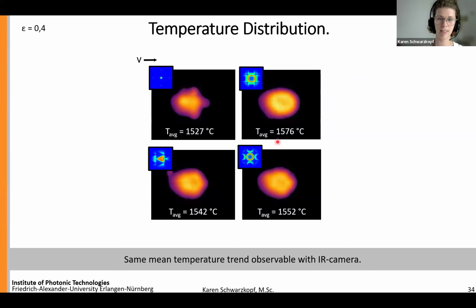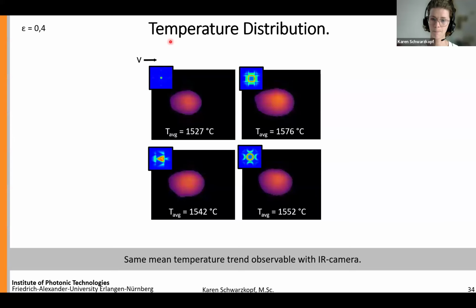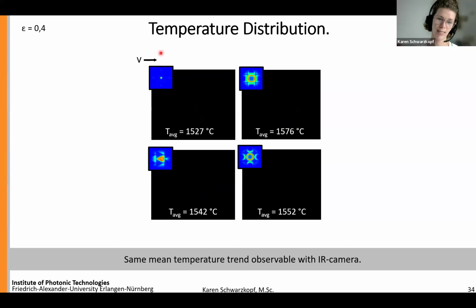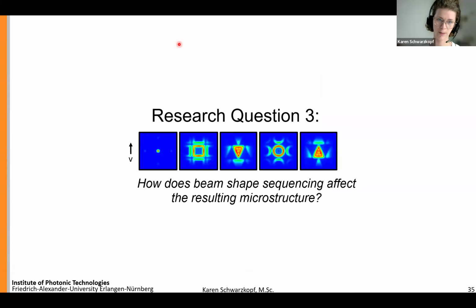Basically, what we can see here is that we have the same tendency regarding our mean temperature. The square and the ring beam profile exhibit higher temperatures compared to the triangular and the point-like profiles. And from this observation, we do expect to see differences also in our microstructure. And this can be seen on the next slide.